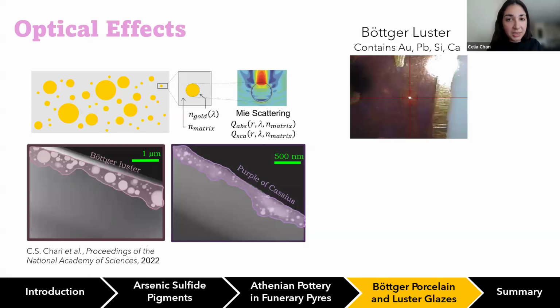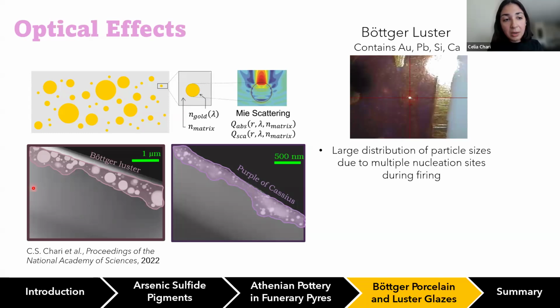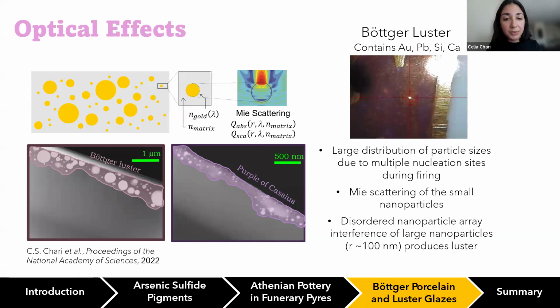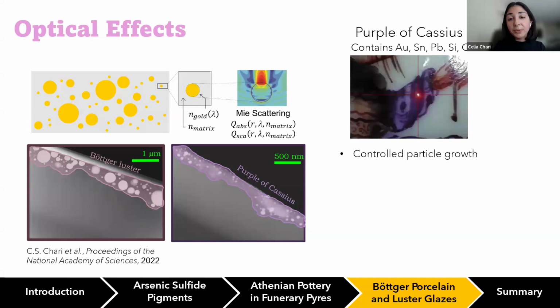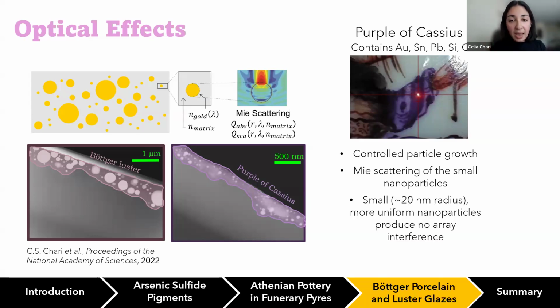But the main conclusion from this is that in Böttger luster, we have both these larger nanoparticles and the smaller ones. The small ones contribute to purple through Mie scattering, while the larger ones create a disordered nanoparticle array that causes these interference effects that make the glaze look more iridescent. In contrast with purple of Cassius, we only see these small nanoparticles because of the control in particle growth that we're observing when tin is present. There's much more of a uniform size. And because we're missing these larger particles, we are not seeing any array interference effects.